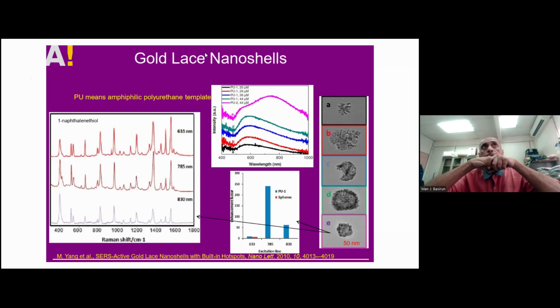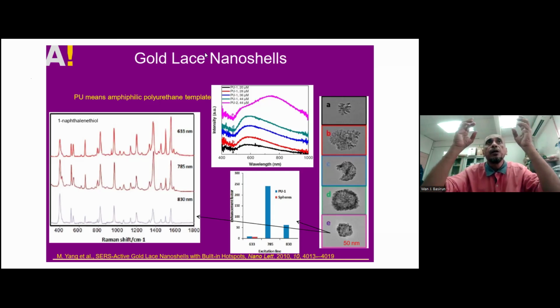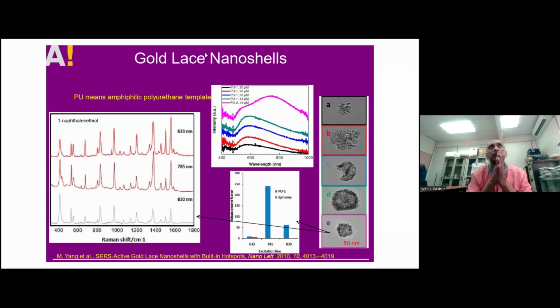Okay. So for example, when you have gold nanoparticles or silver nanoparticles, they must be suspended in a proper solvent, so that solvent is a colloidal solvent. When you suspend it in a certain solvent, it might aggregate, right? But you must find a suitable solvent where you have a colloidal suspension. Colloid is basically a suspension of nanoparticles, and those nanoparticles are kept from joining together by the solvent. You can use, for example, a certain amount of surfactant. That surfactant can separate the nanoparticles from aggregation, because surfactant is basically to disperse, right? For example, a long chain surfactant disperses the nanoparticles from joining up together.